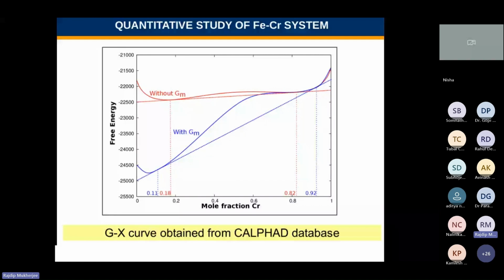And when you want to plot the free energy diagram, you can see this is a particular free energy diagram for the iron-chromium system, and this is without a magnetic part, where you can see again the free energy is a double-well kind of potential, and when you incorporate the magnetic part, it will look like this. But this common tangent tells you that at these two points, these are the equilibrium compositions of these two defined phases. It is phase separating into two phases, right? So for the common tangent, you see the chemical potential of A, the iron in the alpha phase and the beta phase, will be the same, and the chemical potential of B is also the same in both the phases. Then they will be in equilibrium, and these are the equilibrium compositions of these two phases that you can get from the free energy diagram.